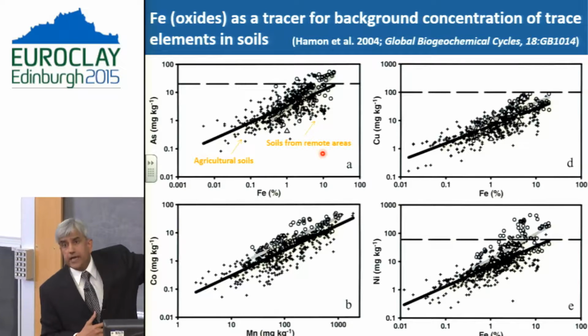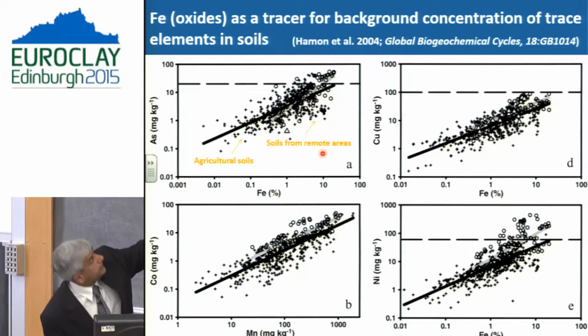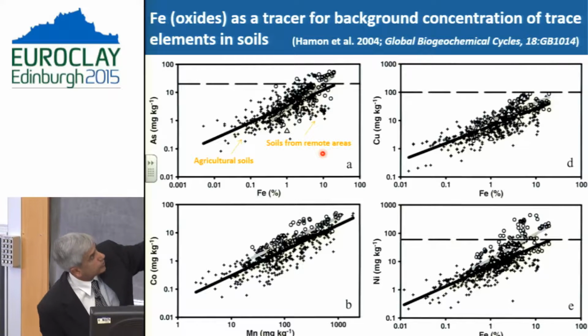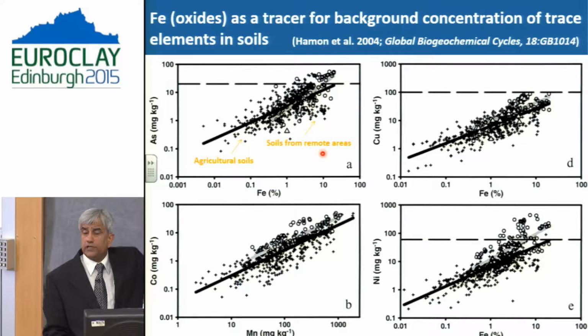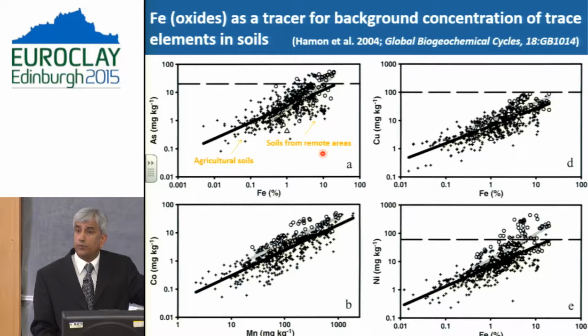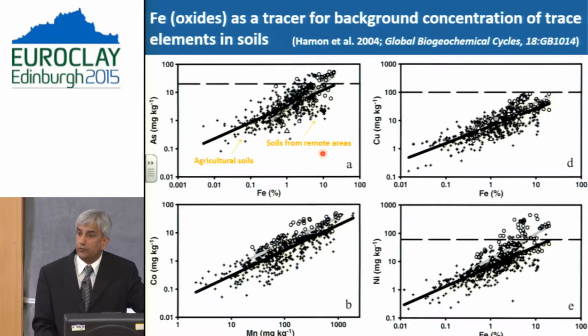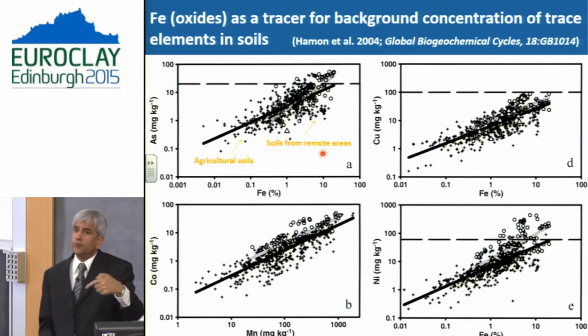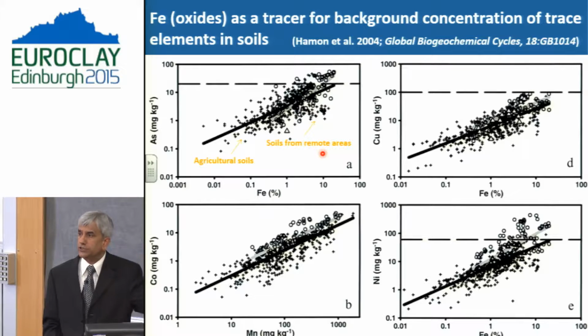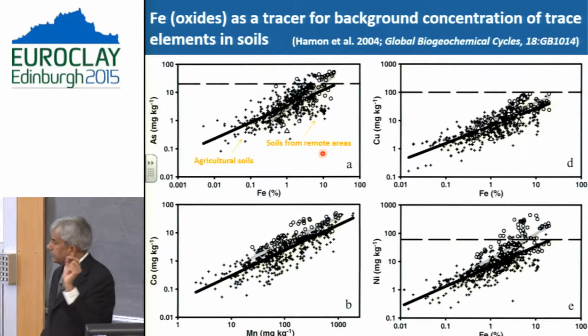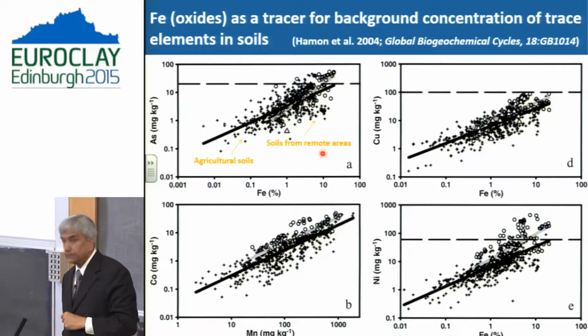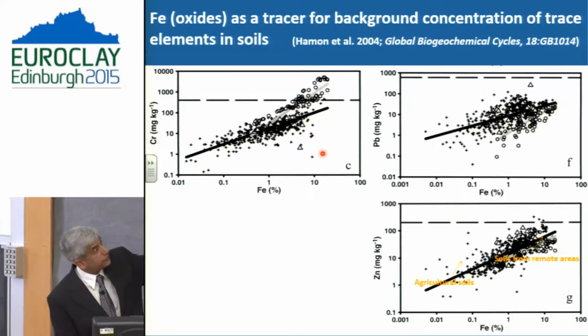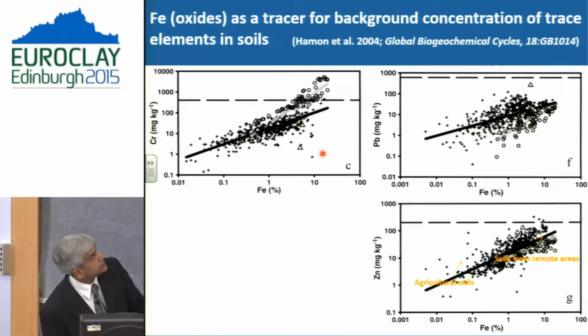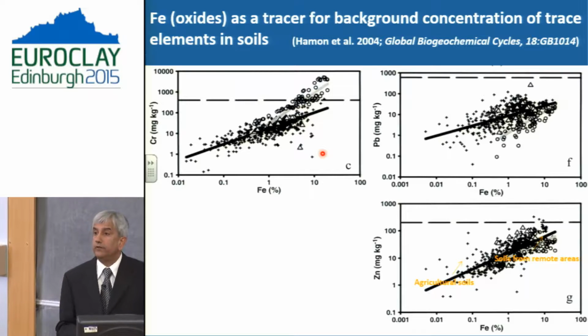So what you see here is that in this case we have got arsenic, copper, cobalt and nickel, and all these elements are broadly associated with iron concentration. So if you want to define the background concentration of these metals, probably you can use iron as a proxy. And it's also true for some of the others as well, chromium, lead and zinc.